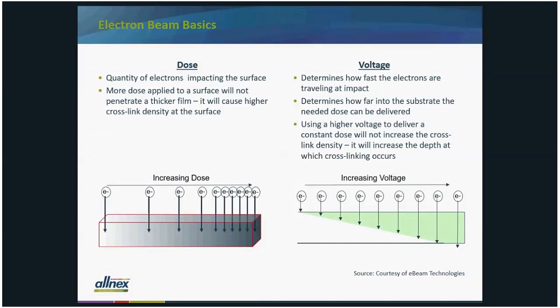By changing the voltage, you can determine how fast the electrons are traveling on impact and how deeply they will penetrate into your coating. So you can use a higher voltage to deliver a constant dose. You won't change the cross-link density, but you will increase the depth of cure. So you have two factors which can be controlled independently of each other to get a precise degree of cure on your coating.